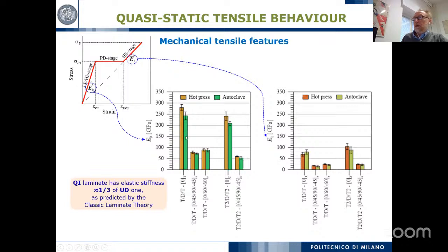But let's go into more detail to distinguish in terms of mechanical property. This is the comparison for both manufacturing processes for all laminates in terms of stiffness at the beginning and stiffness at the end of this stress-strain curve. And you can see that, as mentioned, the manufacturing process does not make a huge difference in terms of mechanical property. As expected, the zero laminate provides higher values for the initial stiffness and also for the final stiffness. The difference between the two sublaminates is mainly due to the increase or decrease in the number of low stiffness ply, and these results can also be quite reasonably predicted by the typical classical laminate theory.